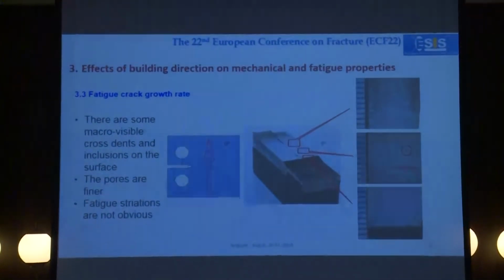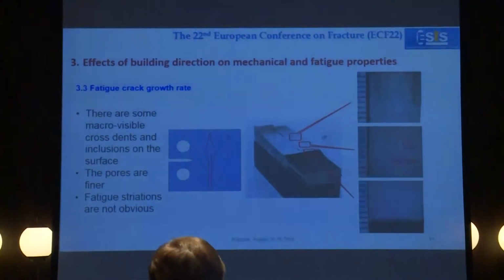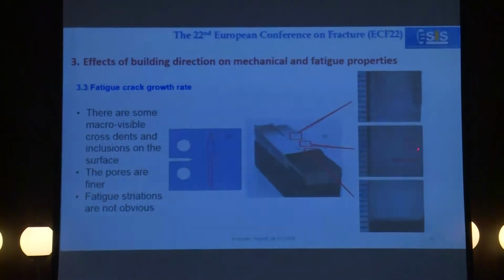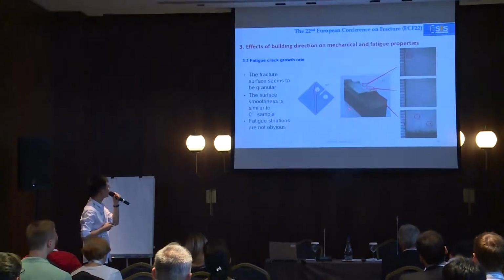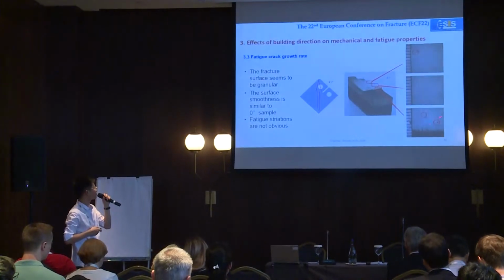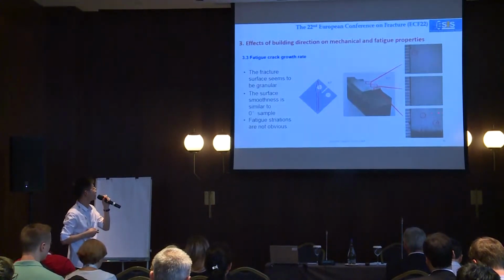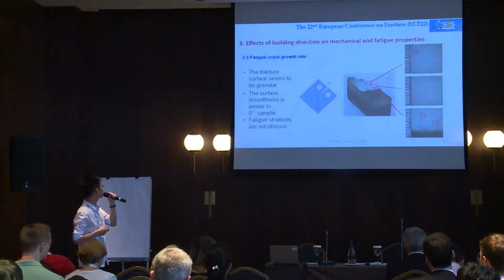This picture shows the fracture surface of 0-degree samples. There are some macroscopic cross dents in the surface. And in microscopes, the inclusions and pores can be observed. This is the inclusion. This is the fracture surface of 45-degree samples. The fracture surface seems to be granular, but in the microscopes, the surface smoothness is similar to the 0-degree samples.